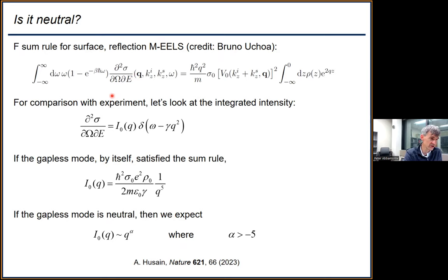The bottom line is, if you write it in terms of the scattering cross section, which is the most useful thing for analyzing the data, then it can be written as an integral over the surface density. If you imagine your demon has some intensity times a thing that's dispersing like Q squared, which is what it actually does in the measurement, you come to the conclusion that the integrated intensity should go like 1/(q^5) if it satisfies the F sum rule. The reason it has this funny form is because we put all the matrix elements and everything in, because that's in the experiment. So this is what you'd compare directly to the raw data. If the thing is neutral, it should go like Q to some power where that power is greater than -5, -5 being what you'd get if it's just, say, a 2D plasmon from a 2D layer or something like that. So this is sort of the last thing in the paper.